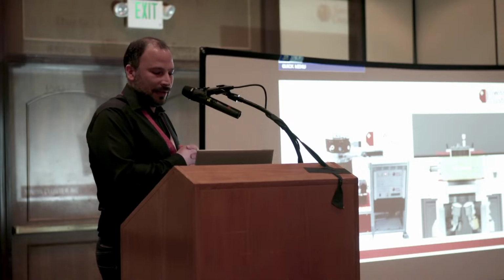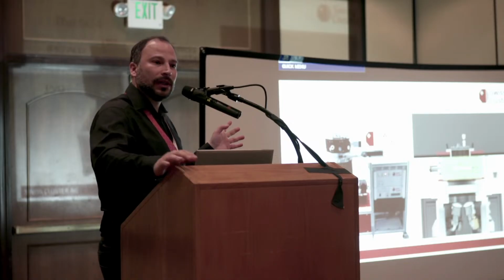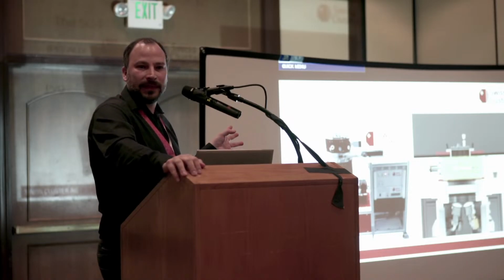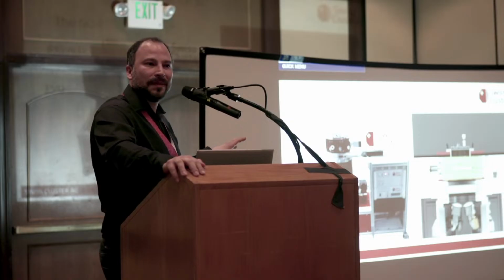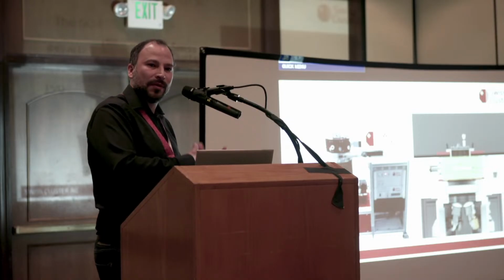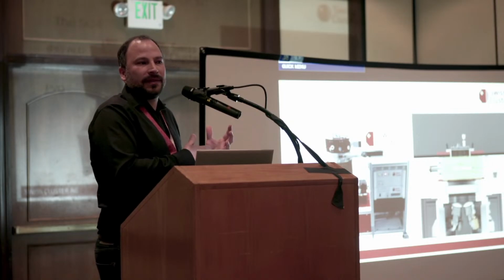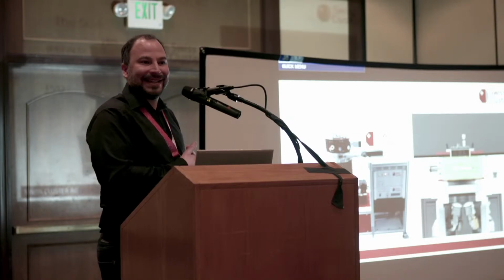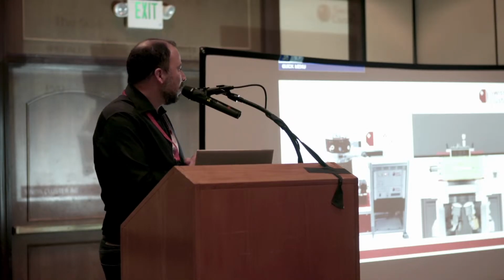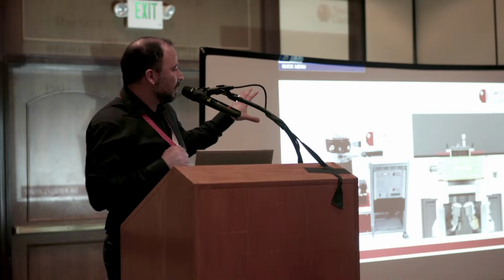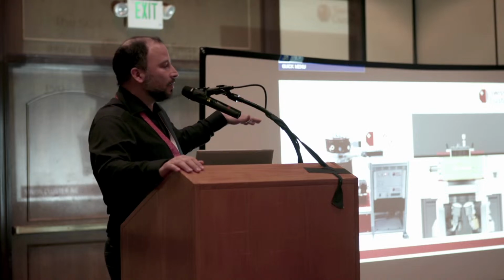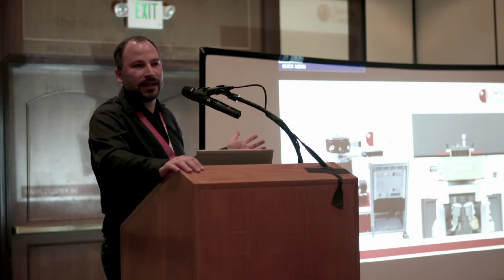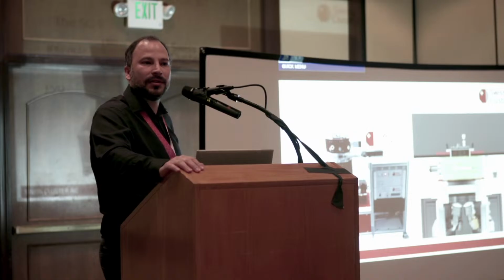Yes, it's a warm wall reactor. It goes to 150. It's an aluminum chamber. It makes it easy to maintain and to replace, so you don't have so much downtime, and it's also less expensive to replace for the customer. 150 degrees on the chamber walls, but on the stage we can go to 800 degrees using a special stage.